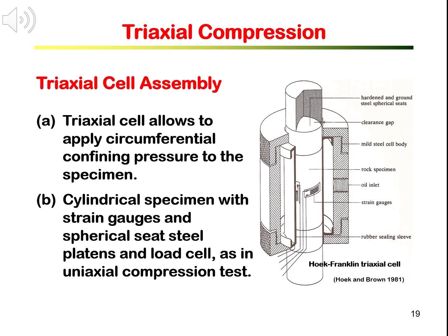The specimen assembly is confined by a rubber sealing sleeve around the circumference and sealed inside the triaxial cell. Oil is injected into the cell through the oil inlet, filling the gap between the cell body and the rubber sleeve. The oil pressure on the rubber sleeve is transmitted to the specimen as a confining pressure.